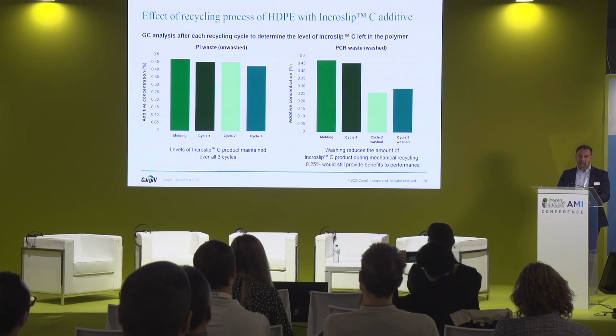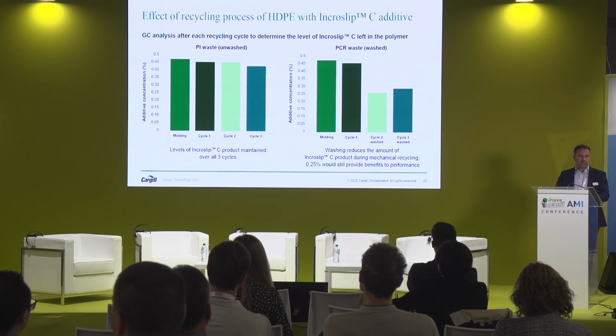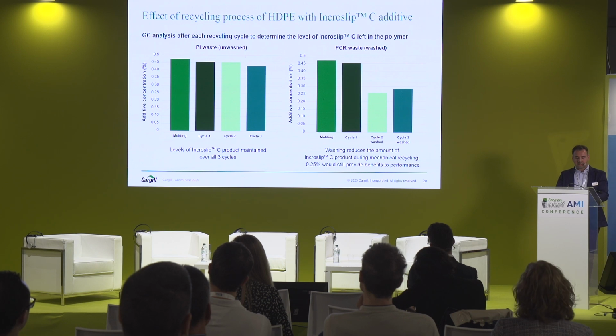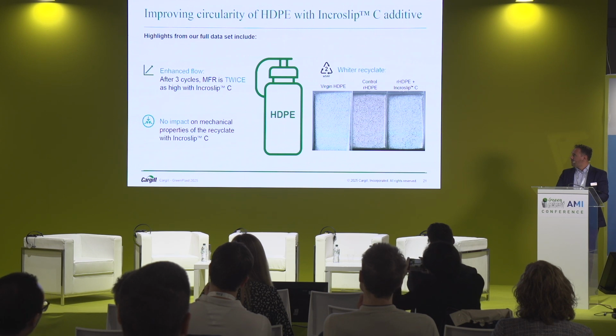We found that there is an effect of washing on the concentration of the additive. So we started with a high concentration of around 0.5%. Then we saw that within 3 cycles it goes down to 0.25, so half of it was lost, but still the remaining amount is enough to give very good effects. And again, this is a summary of the study.